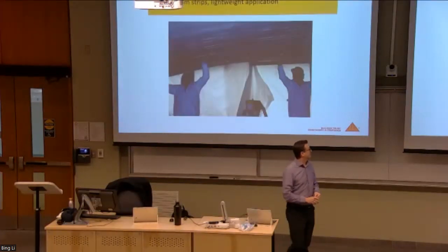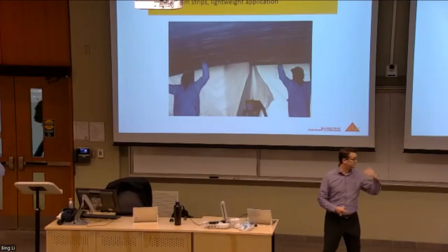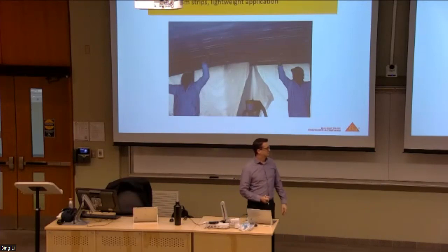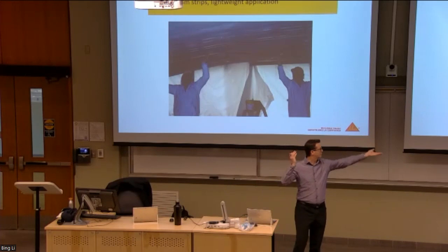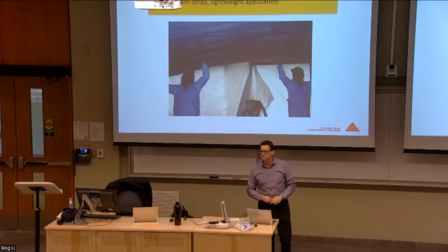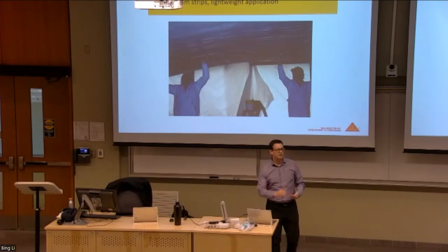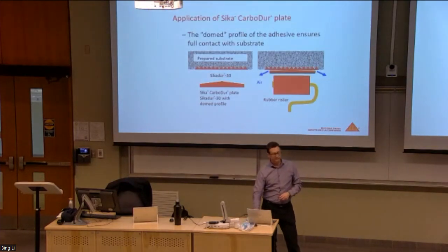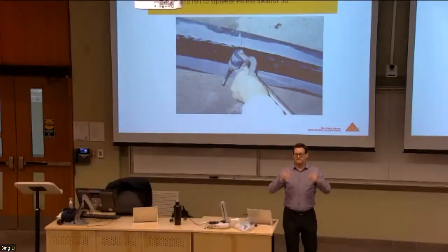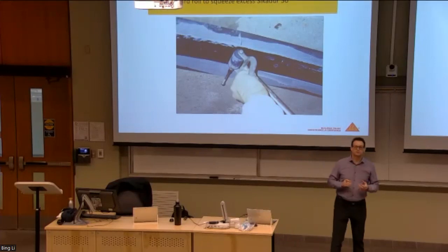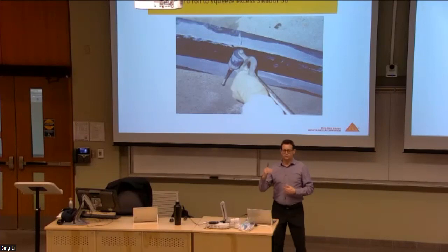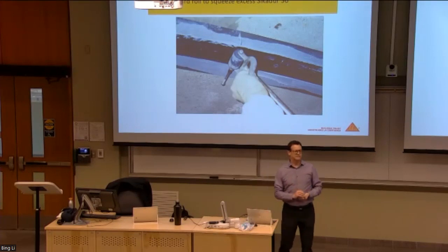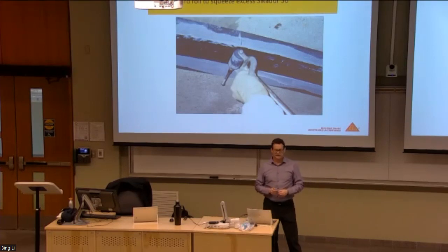Then the workers take it. It was somewhere in the order of from here to the wall in width, so they had about four or five workers lifting it in place. Very lightweight, as I mentioned, and very easy to use. They marry the wet epoxy on the plate to the wet epoxy they've just applied, and then they hard roll it onto the surface and squeeze out the excess, to make sure that we have 100% contact of the epoxy to the plate itself. In principle, in the engineering world, we want to make sure that all of this is acting in unison, much like concrete bonded to steel. We're trying to achieve the same thing when we're designing and applying these products.